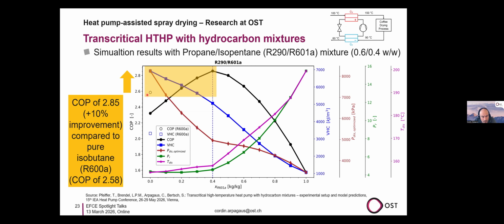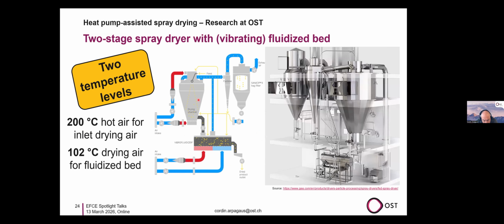So, and now we can see what is the benefit. If you would use only isobutane, pure fluid, then we reach a COP of about 2.6. But with the mixture, we reach 2.85. So 10% improvement of COP just by replacing the working fluid by a more optimal one. And this is the main motivation from research, and hopefully we can convince also suppliers of heat pumps in this direction. Okay, so, but a spray dryer has typically also a fluidized bed and a vibrating fluidized bed.